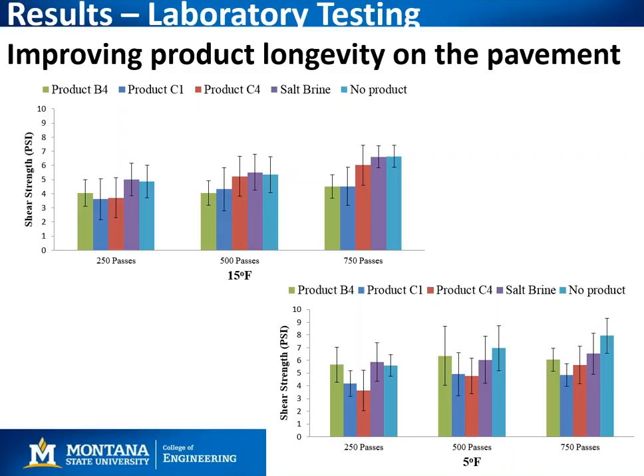But we did it at colder temperatures. We did it at 15 and 5 degrees Fahrenheit. And what you can see is that for the 15 degree, there's a slight trend where it requires slightly more and more strength over time to remove the snow off the pavement. At 5 degrees, it's kind of all over the map. There's a slight trend for some of them that it requires more strength, but for others, it's just kind of uniform. And that at 5 degrees Fahrenheit, it requires a little bit more strength.